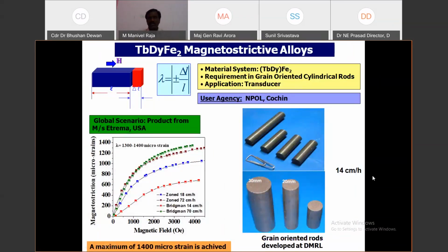DMRL has been working on this material for the last 5 to 6 years, and we have developed the manufacturing technology for making these rods. This is the typical rod of the magnetostrictive material, which is basically dysprosium, terbium, iron. This is the material system that we have developed at DMRL. It is developed by the directional solidification technique, a facility which has been established at DMRL, and we have made the process technology for making the magnetostrictive rods.